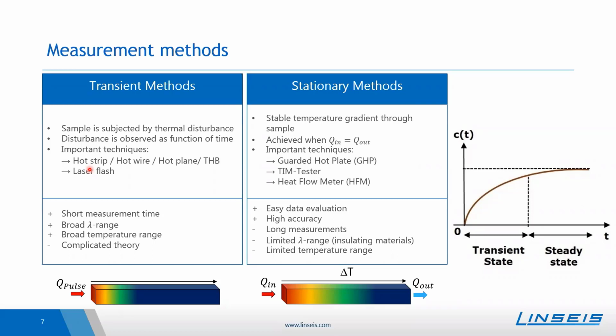The stationary methods, due to the needed waiting time until there is a steady state, take a longer measurement time, but the advantage is that the results will be very accurate and they can be evaluated rather easily. What is a little bit problematic with the stationary methods is that they're typically only for lower conductive materials, so there's a limited thermal conductivity range and also a limited temperature range because it is not so easy to observe the heat flux within a high temperature environment. As already mentioned, the transient hot bridge belongs to the transient methods.